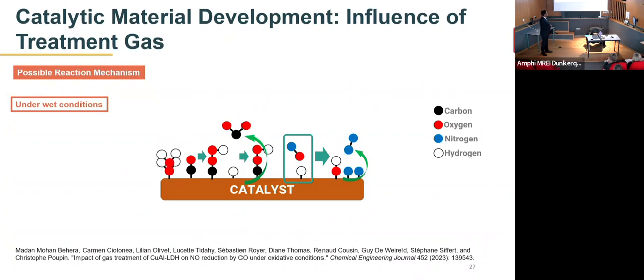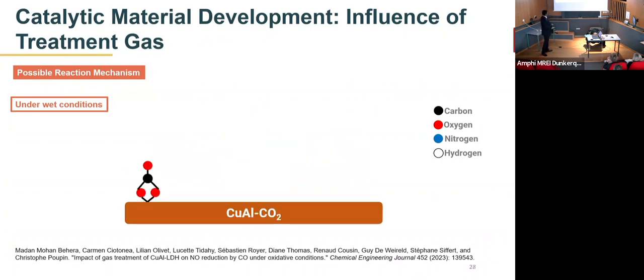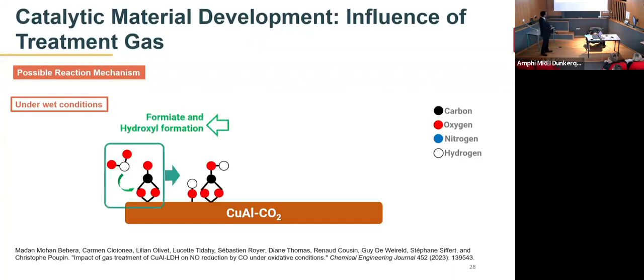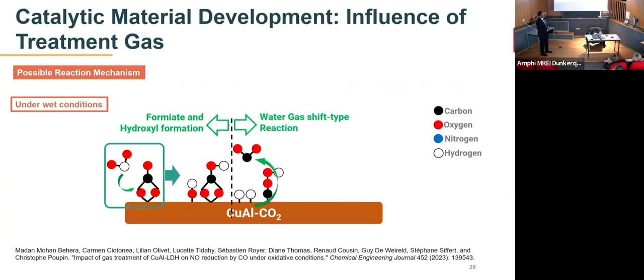Therefore, we suppose that the hydrogen is not released, rather the atomic hydrogen stays on the surface of the catalyst and reacts directly with the nitrogen monoxide from the gas phase to form the dinitrogen. However, in case of the carbon dioxide treated sample, the bidentate carbonates can react with the water molecule to form the formate species and the hydroxyl group. This formate species are generally inactive for our reaction.